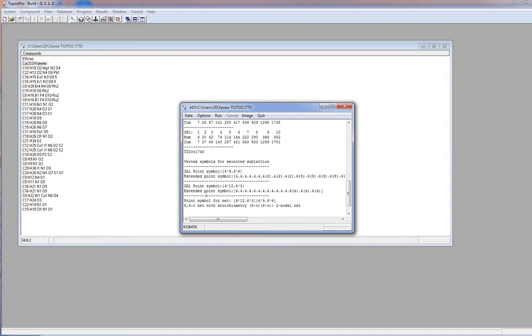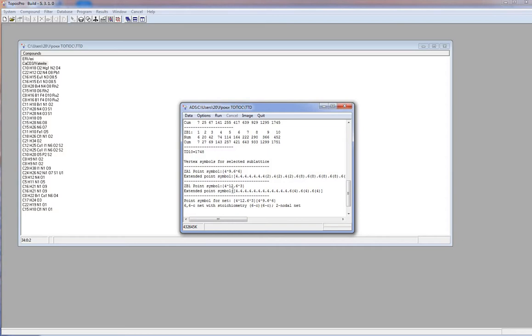Point symbol shows the numbers and sizes of shortest circuits starting from any non-equivalent node in the net. This symbol means that 12 angles at ZB1 pseudo atom contain shortest 4 circuits and 3 angles contain shortest 6 circuits. Extended point symbol shows all shortest circuits for each angle for any non-equivalent atom. This extended point symbol means that 4 6 circuits meet at each of 3 angles and other angles are occupied by one 4 circuit.